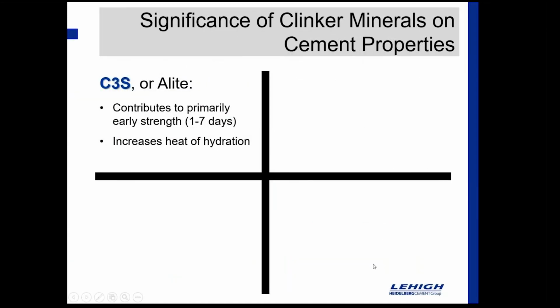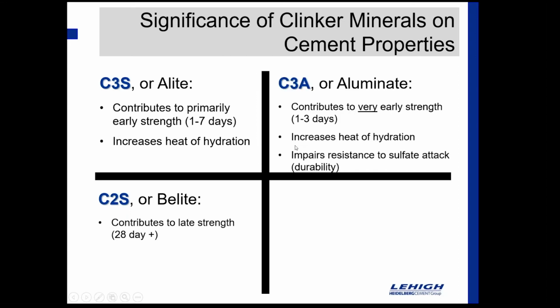So when we talk about how those particular minerals might impact our cement and the performance of that cement, C3S, often called alite, contributes primarily to early strength gain, and that's 1 to 7 days. And as the C3S goes up, you could expect to see an increase in the heat of hydration as well. C2S, or often called belite, primarily contributes just to the later age strengths, and we're looking at 28 days and beyond kind of strength gains. So not a lot of heat from C2S early on, but that's where you get that kick that you're used to seeing at 28 days.